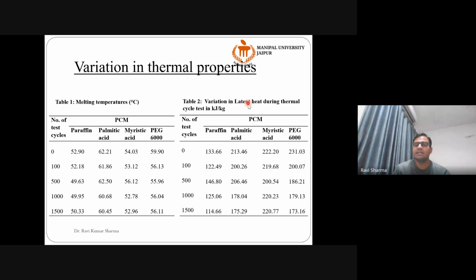The variation in latent heat in the case of paraffin went from 133 to 114, that means a 14% reduction. In the case of palmitic acid, it was 17.88%, roughly 18%. In myristic acid, only 0.64%, but in the case of polyethylene glycol, it is roughly 25%.